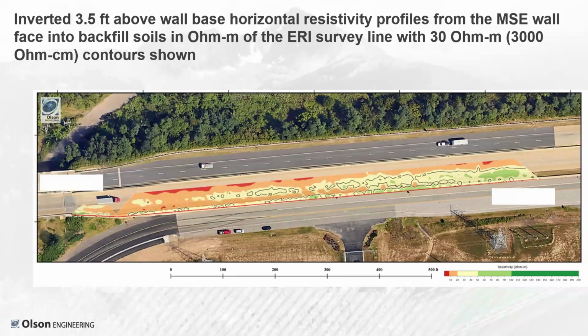I would like to note further towards the median of the road, we have what we would interpret as very corrosive material as seen in red and orange closer to the road. However, I would like to note that this is an interesting use case for resistivity, where we have basically an air void above us, which is the top of the road. So when you're interpreting this, it's very important to keep in mind that you have this air void that might be causing sort of artifacts in your data.